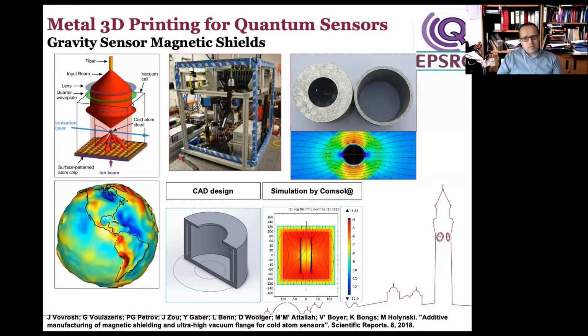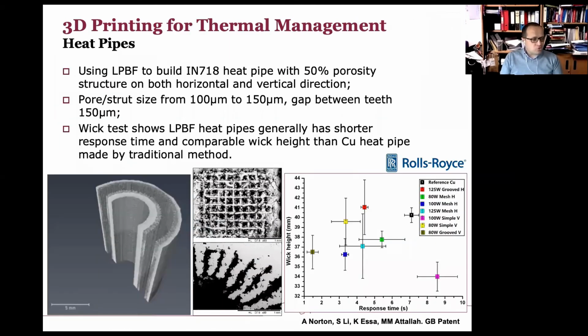I'll move into another application, also onto how we tailor material, or how we tailor the topology of the material and where we put it. We did a while ago a project with Rolls-Royce looking into efficient cooling, and that was through the use of what's known as heat pipes. These heat pipes are typically made out of copper with powders inside, and they achieve cooling through the so-called wicking behavior, where the liquid just goes through the height and allows for heat to be lost through the component.